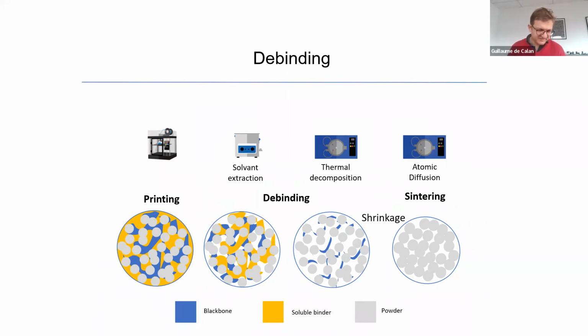We will probably, out of experience with other materials, see a slight difference between printed silicon carbide and silicon carbide done by traditional means in terms of bending strength. We usually see a slight offset, typically a bit lower than the bulk material, something like 10-15% lower, especially in the Z axis.